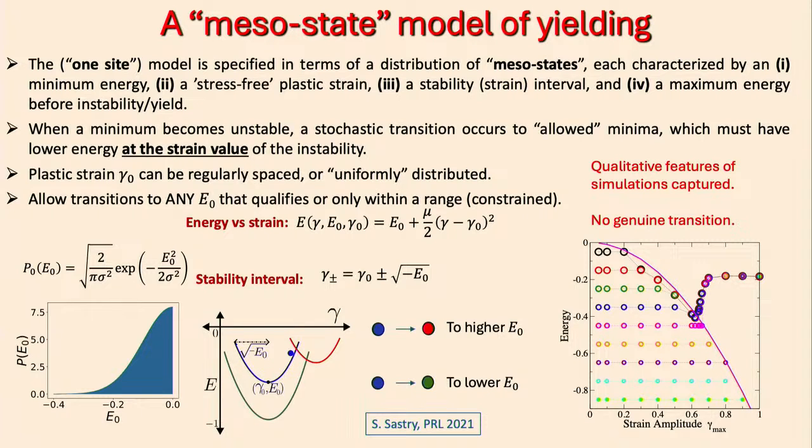Okay, there are interesting differences, but the basic features that are reproduced are when I start with a poorly annealed glass, which is high energy, I have initial annealing before I yield as I ramp up the strain amplitude, whereas if I sit at a very low energy state, I do nothing till I reach some amplitude at which I make a discontinuous jump.